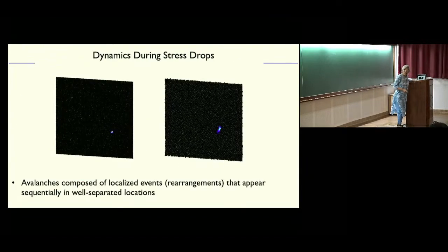But if you look at the dynamics, if we go back to Ludovic Berthier's system, here's a system that doesn't show strain localization, and here's the one that does: the ductile on the left, the brittle on the right. In the ductile case, you see these very tiny little rearrangements, flashing in and out. All these stress drops can be decomposed into these very localized events. Now let's look at the huge stress drop that occurs in the brittle case. It looks the same. The only difference is that the rearrangements are all concentrated in this region that becomes the shear band. But the dynamics are localized rearrangements, and because we have localized rearrangements, a localized quantity like softness, we think, is useful.